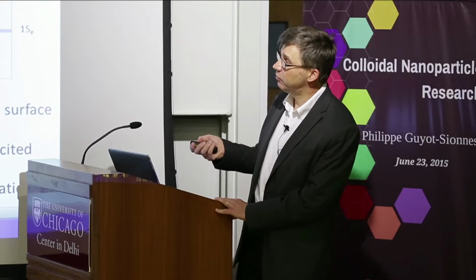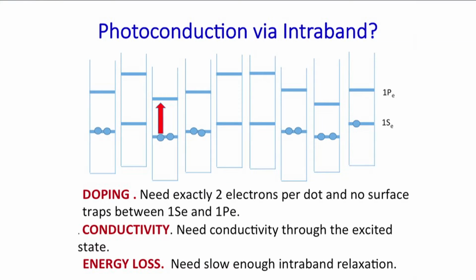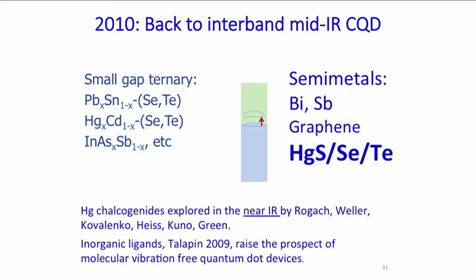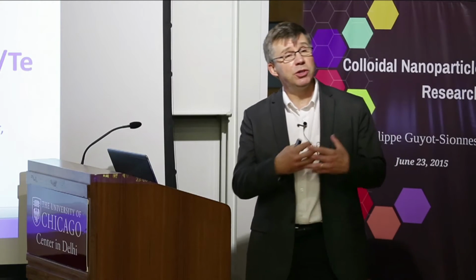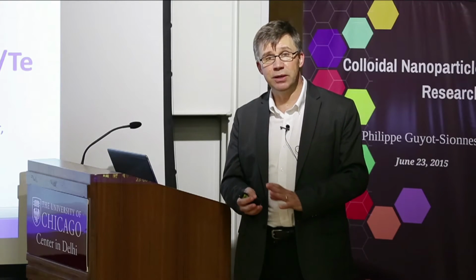And when we started, this was not very promising. The electron was coming down in a picosecond or less. So a picosecond is a pretty short time. It would require mobility as high as the highest mobility presently achieved to have an electron hop over in also a picosecond. So that was certainly not possible. So we thought about this for several years, 12 years, didn't make any progress. Eventually we gave up, and we moved back to the simpler idea of using quantum dots that would be made of a material that already had a band gap in the infrared, quite far.